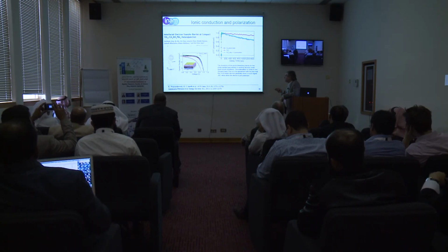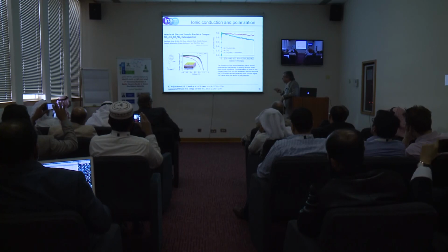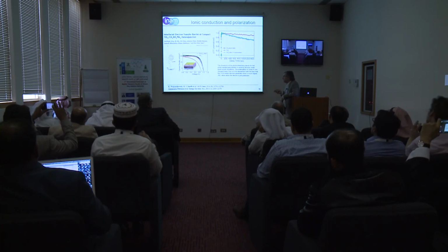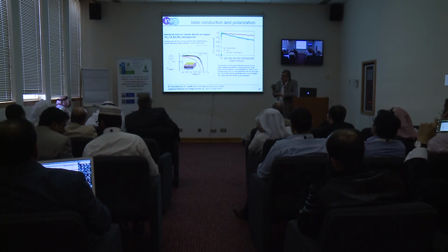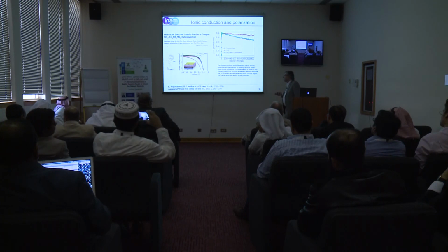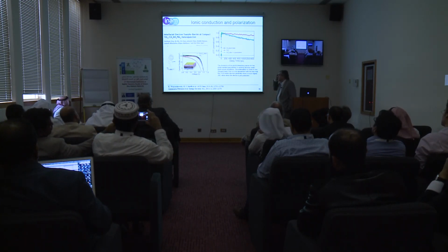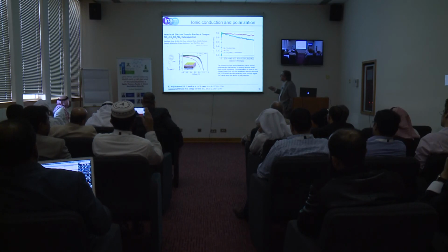So, for example, this is the modification showing that the modification of the contact TiO2, including some fullerene, removes a big hysteresis in the planar cell. The planar TiO2 solar cell has a very big hysteresis for some reason, maybe related to my interpretation. But when you put some carbon material in the electron conductor, then you remove almost totally this hysteresis.